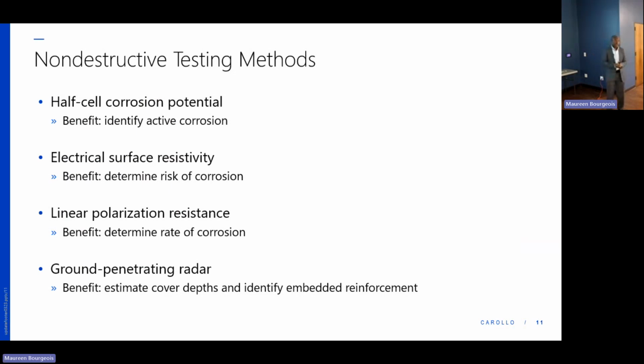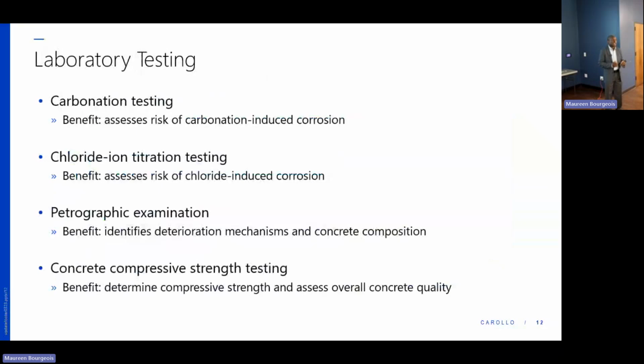Let's get to the laboratory testing. So whilst we can do this, the earlier one, which is using equipment, there's still stuff that we generally cannot see. And that we have to go into the lab to do some more in-depth study. And so for the structures, we took cores. Basically, we drill a core sample, which is a 4-inch diameter by 8-inch long sample from the structure, concrete piece. So we extract that out, and then we test it in the lab.